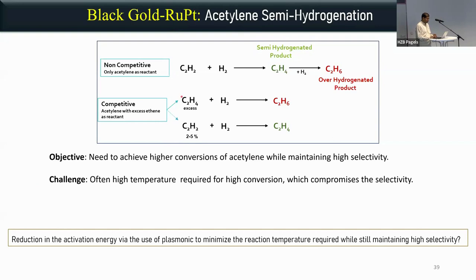Another interesting reaction that we try to carry out is acetylene semi-hydrogenation. You want to convert the acetylene into ethene without going to ethane. You want to stop at ethene without going to ethane, so that's why it is called semi-hydrogenation. And more interestingly, that acetylene is only 2%, and 98% is already ethene. So this is an industrially relevant process where you have ethene with 2% or 5% acetylene as a contamination, and you want to only convert that 5% acetylene into ethene without touching the ethene and converting it to ethane. So we said, can we use the plasmonic concept in doing this reaction?